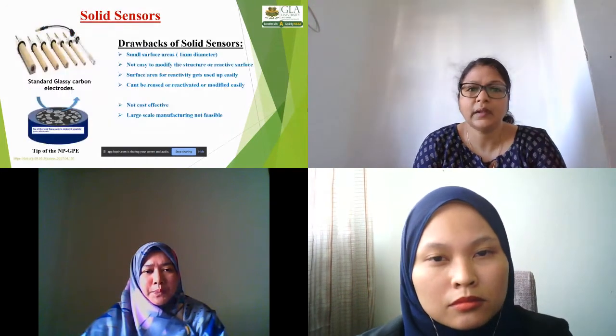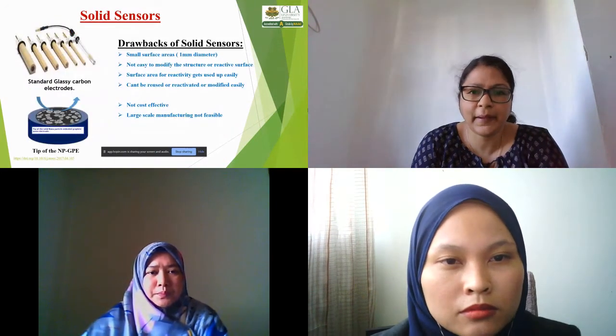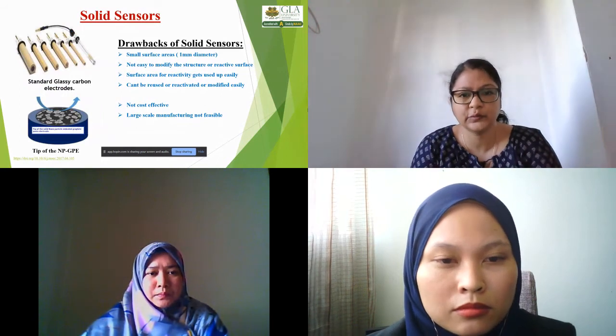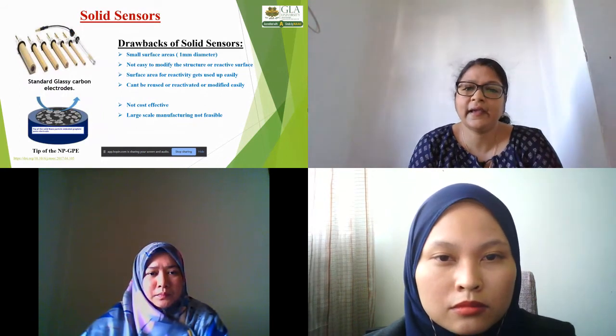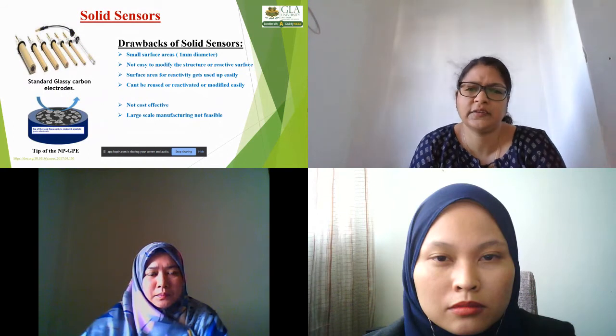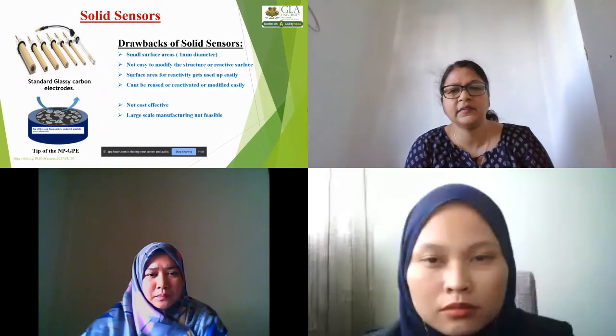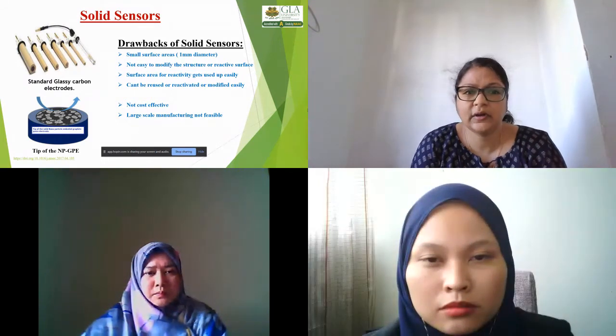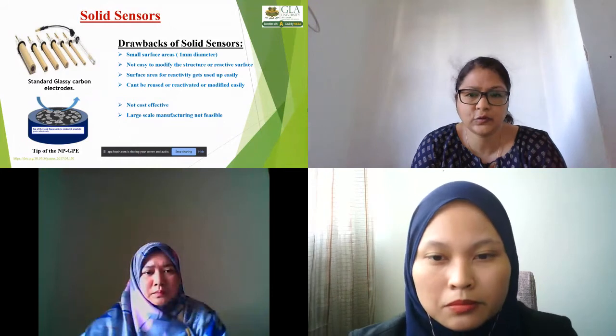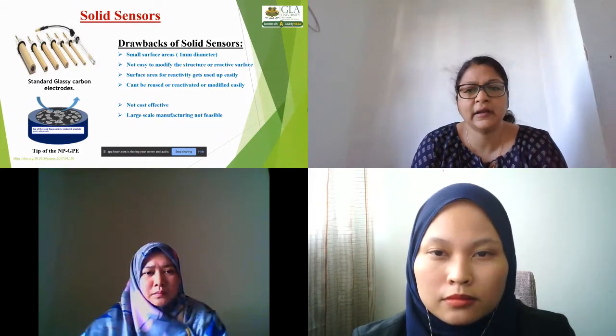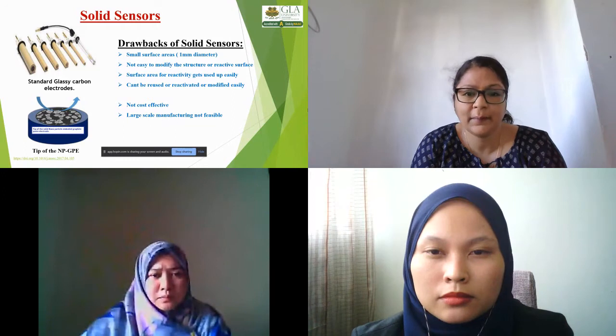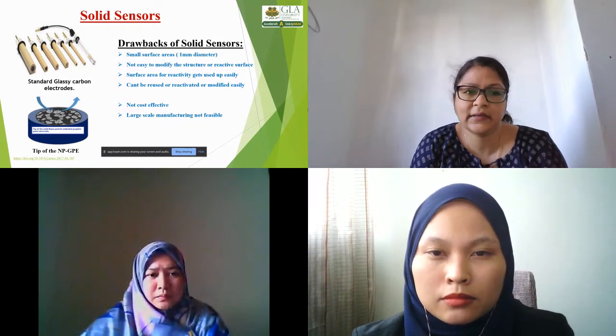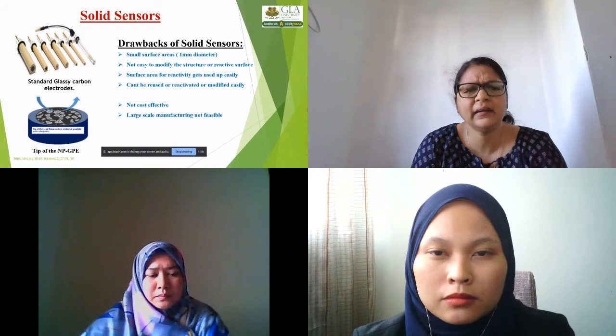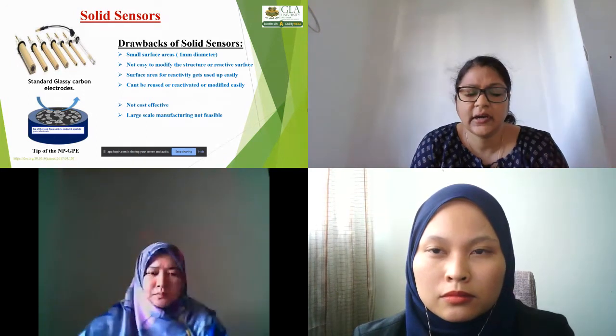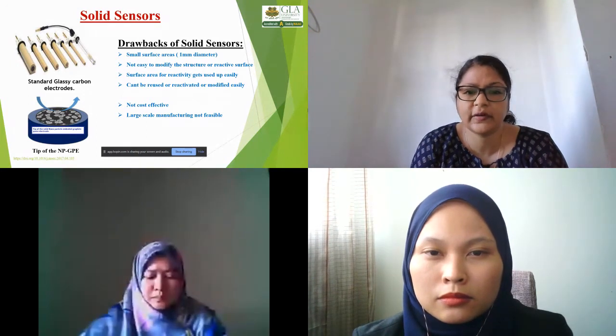But the drawbacks of the solid electrode, which led us to move to polymeric sensors, are that they have a small surface area, mostly 1 millimeter diameter at the tip, and this is not easily modifiable. The reactive surface being so small easily gets used up and cannot be reactivated easily, and because it has a rigid structure, its modification is also very hard.